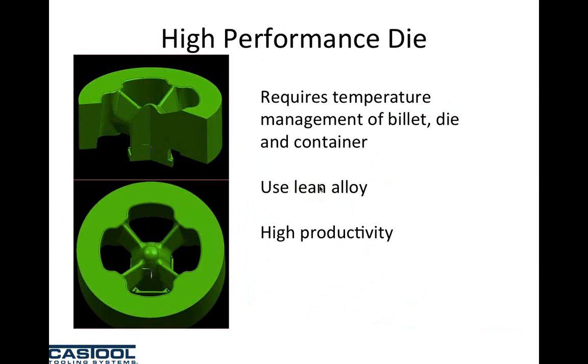The alternative is a high-performance die. They require temperature management of the billet, die, and the container. Very often the same people that are using these dies are using lean alloys. What they're achieving is ram speeds typically 40 to 50% faster than the average that we see in the marketplace.